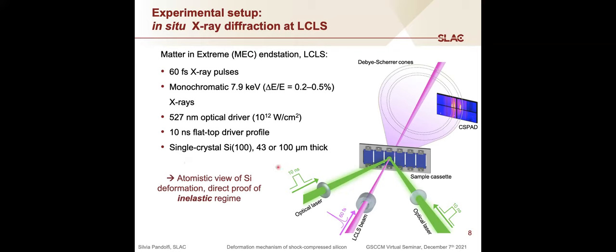And we have used single crystal samples to be able to individuate not only the phase transitions, but also the orientation and the texture changes in the sample. And we have used a very highly monochromatic X-ray probe, which ensures high fidelity when we analyze the orientation and the evolution of a single crystalline sample, and used the long pulse laser at the MEC instrument to compress the sample.